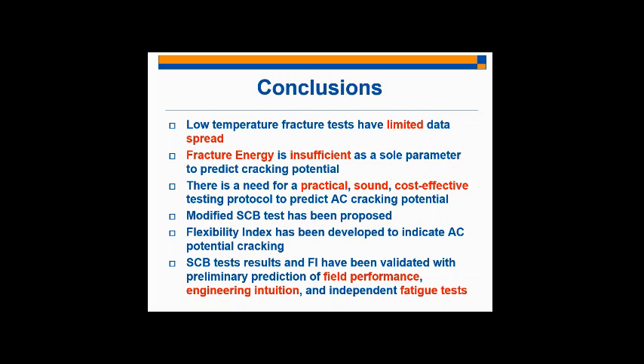And we've developed a flexibility index that has shown significant promise in indicating cracking potential for field mixtures and has matched engineering intuition. We've also shown significant correlation to an independent fatigue test, the TOL Texas overlay test. We were able to match the extremes of the performance spectrum. The excellent mixtures from both tests matched, and the poor performing mixtures from both tests matched.